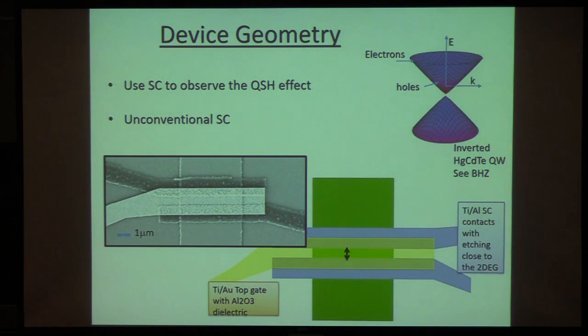So what's the system? The system actually is a very, very simple one, as I mentioned before. It's just a Josephson junction. It's shown here. There is a superconductor, another superconductor, and in between there is material that has strong spin-orbit interaction. And the specific material that we have explored up to now has been mercury telluride. There have been a variety of good reasons to use that material, but in fact now we're collaborating with Javad, trying to realize the same kind of experiments that I'll describe in a system where we replace the mercury telluride, the semiconductor, with indium arsenide, yet another conventional semiconductor that just has some nice spin-orbit properties that are useful for this physics.